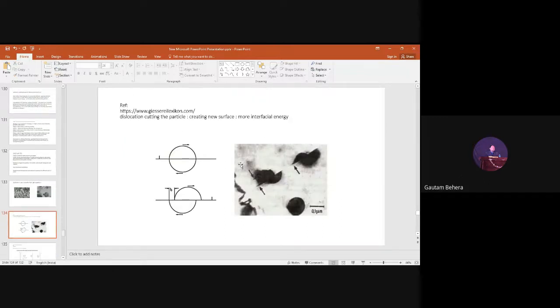Now this is a very good image which shows dislocation and particle interaction. Basically, if you remember, in the previous lecture we discussed what happens to the precipitate particle when it is small and coherent. You can see this is the dislocation. This is the plane on which the dislocation is gliding. The dislocation is now interacting with the precipitate, and this is the consequence of that. You can see the dislocation is shearing or cutting the precipitate particle if it is a small and coherent one, right? And it is coming out now here. This is a real TEM image.